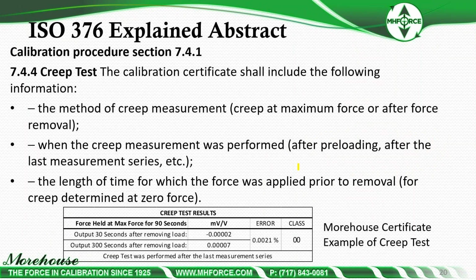So on the certificate, ISO requires the method of creep measurement, creep at maximum force or after force removal. When the creep measurement was performed after preloading, after the last measurement series, the length of time at which the force was applied prior to removal for creep determined at zero force. And then you get down here and you look at our certificate and you say here, force held at max force for 90 seconds, output 30 seconds was negative 0.00002, output after 300 seconds. There's a formula to do this error, class assignment here. And then at the end, lots of labs miss this as well, this requirement to report on the certificate, which is creep test was performed after the last measurement series.